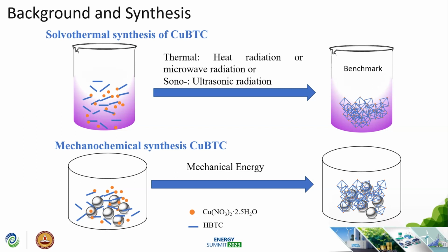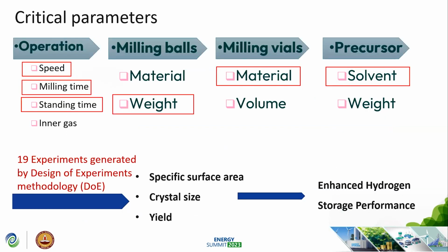However, in this method, we also have some parameters we need to solve. For example, there are a lot of reaction parameters in this method that will influence the property of the copper BTC. In my research, I used the design of experiments methodology to generate 19 experiments to explore the influence of the 6 parameters on the properties of copper BTC: specific surface area, crystal size, and yield. The 6 parameters include rotational speed, milling time, standing time, ball weight, starting materials, and the solvents.